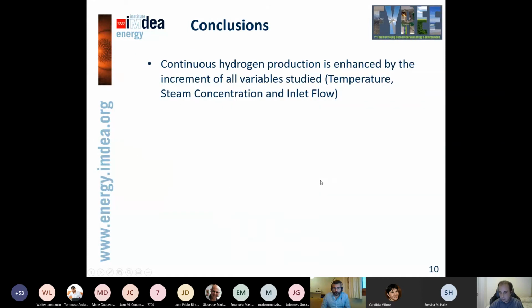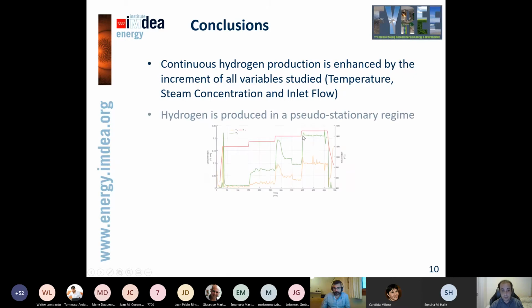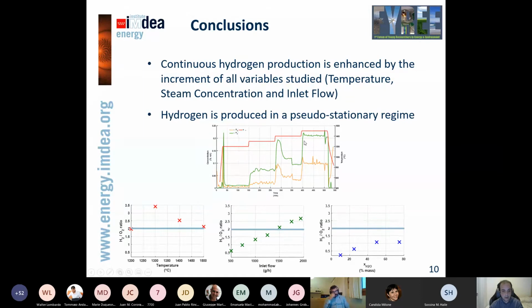So, just to conclude and give a brief overview of this work, we were able to continuously produce hydrogen, and this production is enhanced by the increment of all three variables that we studied. Additionally, we can consider that hydrogen is produced in a pseudo-stationary regime. Let's say that in almost every step at 1300 degrees C there was this peak and also this value, but you can see that there are plateaus at every temperature, and this happens for all tests. But if we check the hydrogen-oxygen ratio, we see that this is not what is expected for a thermodynamic equilibrium.